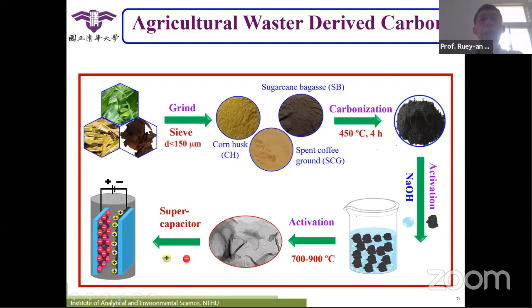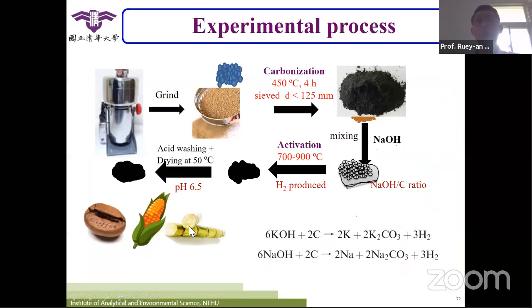Okay, so we can try to use, for example, corn leaf, coffee bean grounds, or sugarcane bagasse. We grind them and fabricate very simply to form carbon, to form the supercapacitor or the CDI or some biochar. We just use this very simple grinding and carbonization for 4 hours, then activation at around 700 to 900, and then we can get very good material.